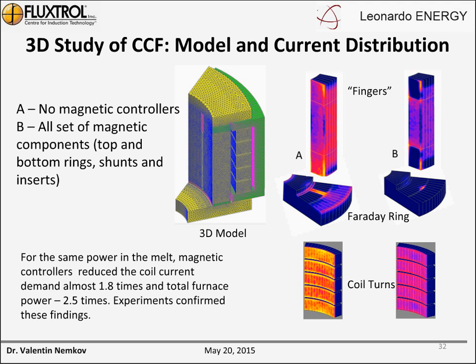What are inserts? Inserts are the realization of the idea that on the top and the bottom, the part of the system where magnetic flux should go through the fingers, we expand the gap or part of the gap and place there some magnetic material, soft magnetic composite, that can help magnetic flux to penetrate through these narrow areas. You can see here the 3D model, and then you have A from top to bottom.